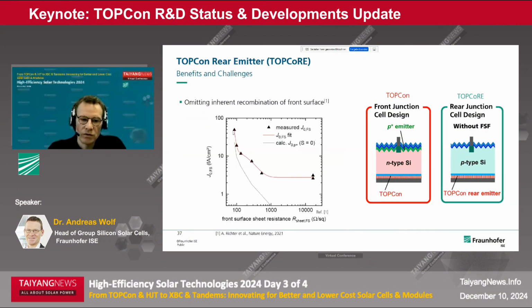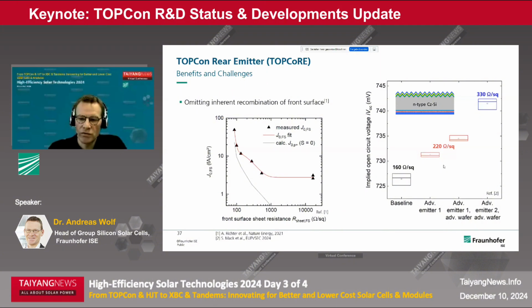So here you see the recombination parameter of this front emitter versus the sheet resistance. And of course, if you increase the sheet resistance, you decrease the recombination parameter. And it is known that you can achieve very high implied VOC values when increasing sheet resistance, which has been implemented in industry in the past years. But still, there is an intrinsic recombination, that is this gray line, which is Auger recombination linked to the doping itself that you cannot omit. And at current sheet resistance values, this still covers about 1.5 femtoampere per centimeter squared that is inherently present when you have a front doped layer. And this could be omitted by using the TOPCORE cell structure.